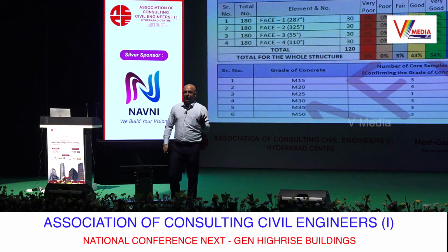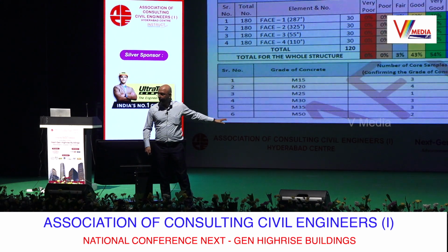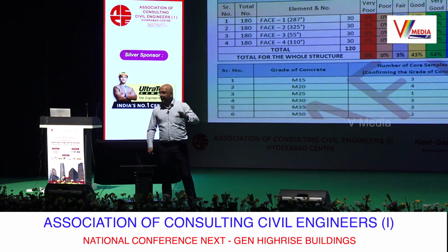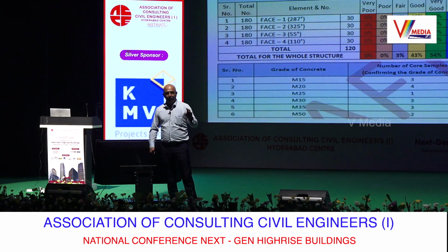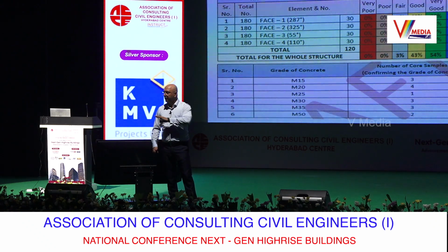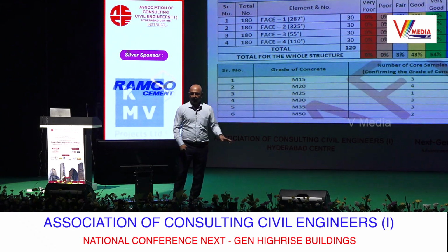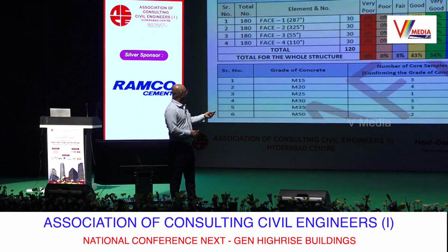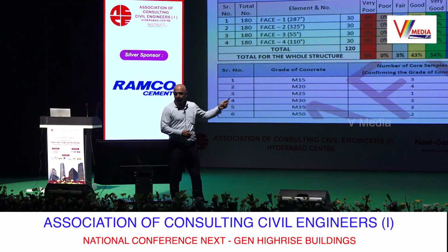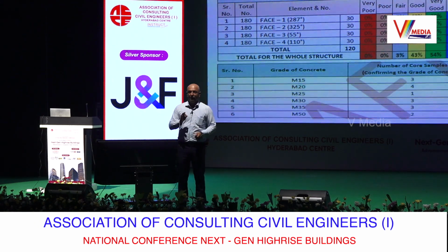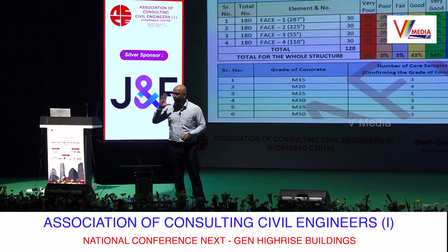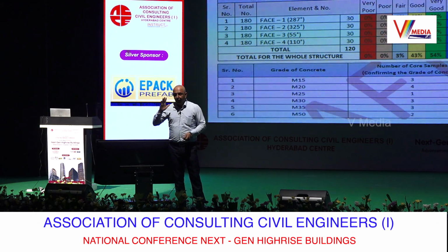You should never use epoxy mortar in this kind of repair, because properties like coefficient of thermal expansion, creep, modulus of elasticity, and drying shrinkage will all differ from the original concrete. So don't use this in patches. When we did a GPR scan, we realized that the reinforcement provided in the most critical zone was less by 20-30%, or in some cases even more than 35%.